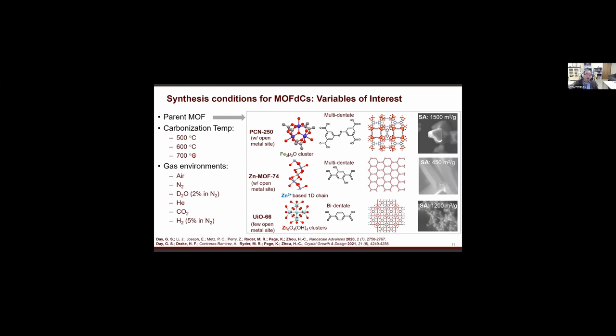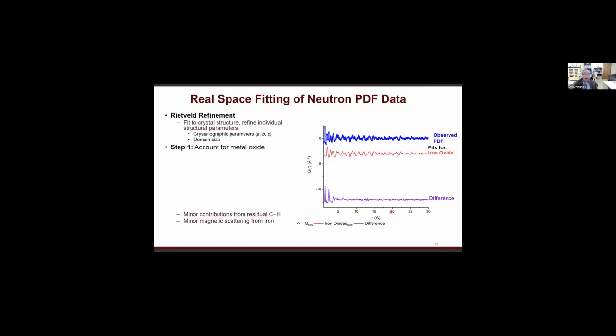Then we set the carbonization temperature at 500, 600 and 700, and under different environments: air, nitrogen, 2% D2O in nitrogen, helium, carbon dioxide, and hydrogen 5% in nitrogen. Once we set up all these experiments, we perform the calcination and then collect the neutron PDF data.